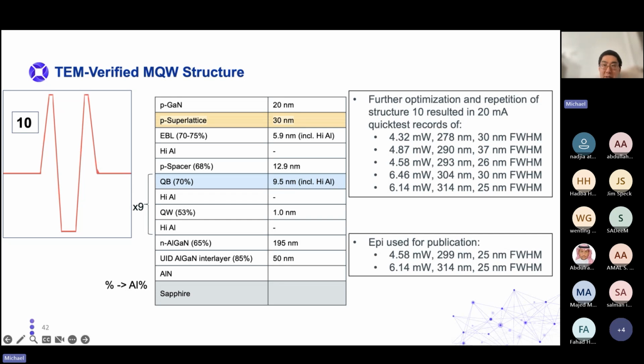And further optimization and repetition of this structure resulted in quick test records at different wavelengths of 4.3 milliwatts at 278, 4.8 at 290, 4.5 at 293, 6.4 at 304, and 6.1 milliwatts at 314 nanometers. And the epi that I used to publish were these two. So 4.58 at 299, so the 300 nanometer LED, which ended up being 18% efficient in terms of EQE, and 6.14, which ended up being 20% efficient in EQE. The 300 nanometer one was, I believe, 18% in wall plug, and the 6 milliwatt one was 16% in wall plug.